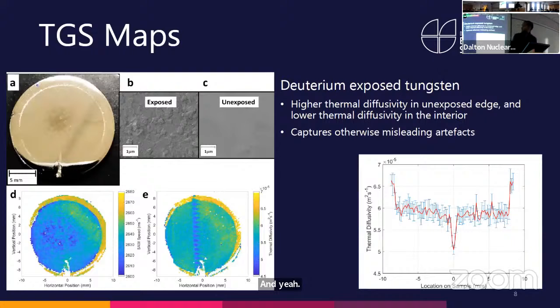Yeah, and this is a sample we did. This was deuterium implanted tungsten, where the outer bits were shielded from the deuterium plasma, and the interior was exposed to the plasma. And you see the exposed regions have these blisters on them, but they measured quite well in TGS. These were the samples we were mentioning earlier. And you had low thermal diffusivity in the center, and high in the unimplanted edges. Same with the acoustic wave speed.